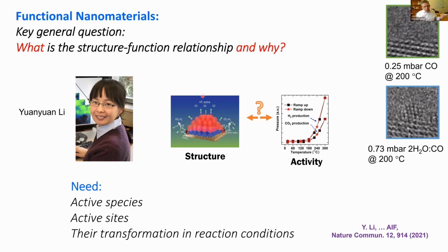And so this represents to me a generally formulated research project. The research purpose is, if you have structural measurement and if you have activity measurement, how do you link them together to understand catalytic mechanisms? By the way, the reason that you don't see the atomic positions so clearly under CO is because of strong CO binding to the surface of the platinum nanoparticle. The repulsive interaction of the CO molecules causes platinum atoms to move out of their regular positions, causing significant strain. That is the reason why you don't see anything there.